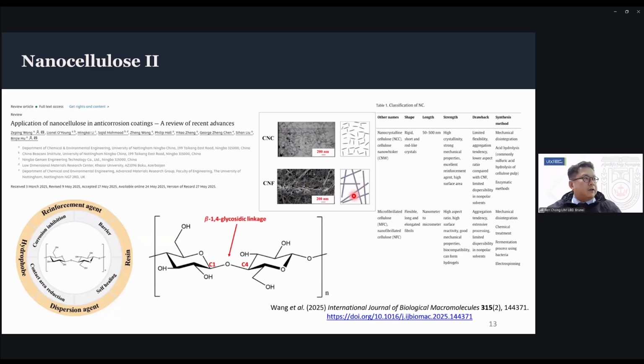These are like long filaments, ranging from nanometers to micrometers, but the diameter is still on the scale of nanometers. The one on top is nanocrystalline cellulose, which is more like rods, usually 50 to 500 nanometers long. The diameter is also around that size, and both normally have good crystallinity and good mechanical properties.